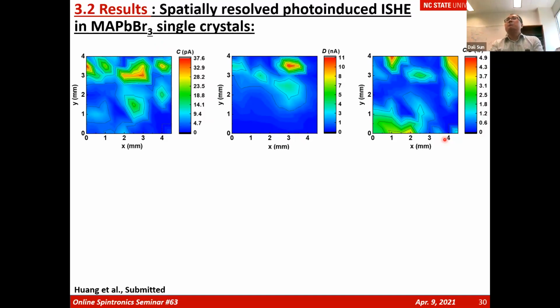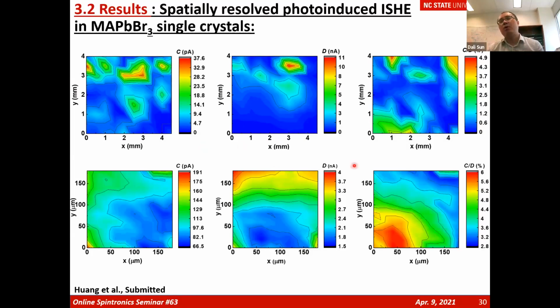Actually, we found it's not. We're measuring the bulk photocurrent conductivity across the whole surface of the crystal, like 4 or 5 millimeters by 5 millimeters. At a certain spot, we see higher photocurrent densities because of morphology, roughness, and the optical absorption. But even normalized by the photoconductivities, we found the spin component showing a spatially resolved distribution across the whole surface. It's not uniform. Only on some certain points, in this zoomed-in picture around this area, in some certain spots, the photo-induced ISHE response is maximized. Only on certain spots, not the whole surface.